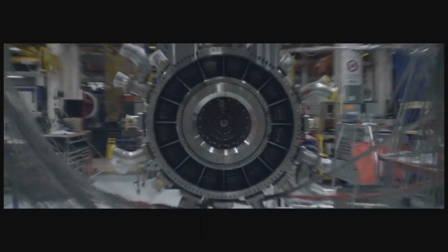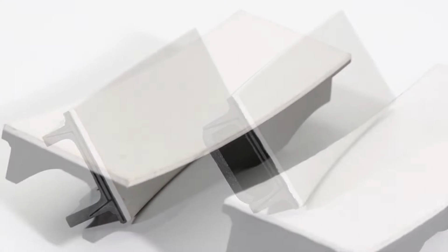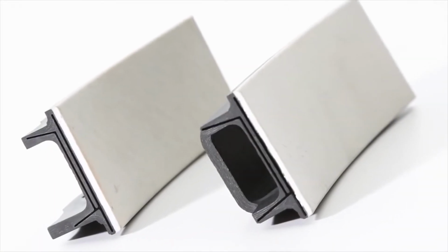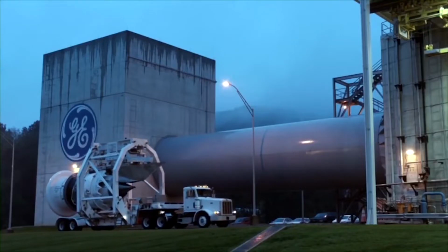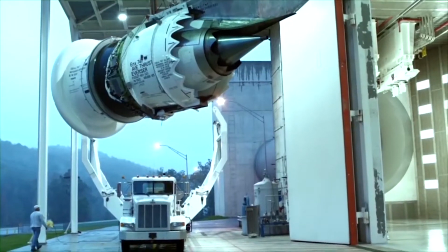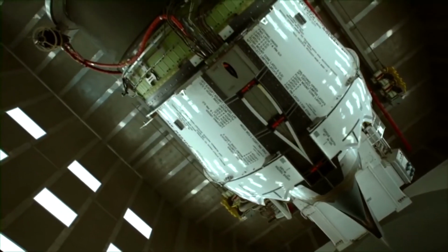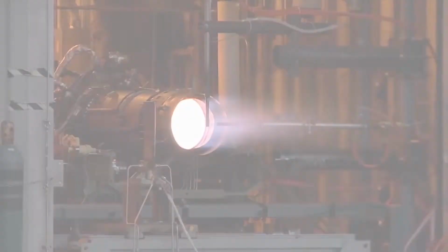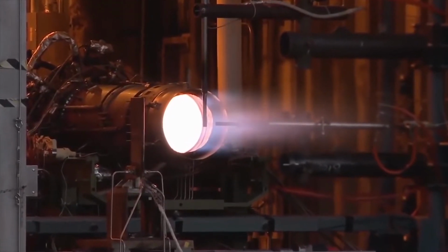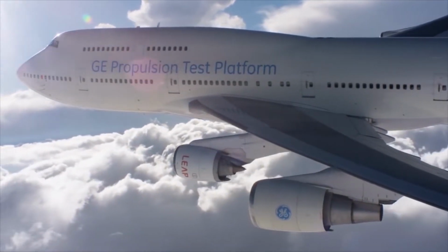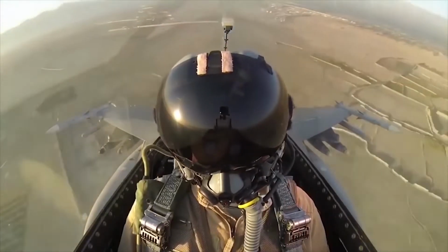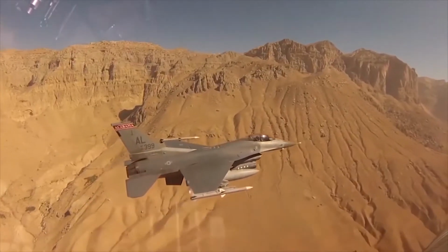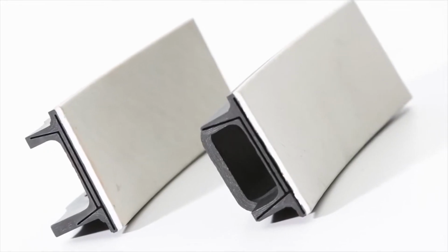For 20 years, GE has been at the forefront of CMC research, developing a material stronger than metal that can tolerate heat more than 500 degrees higher than any alloy, yet it weighs 2/3 less. CMCs are already at work in GE's newer jet engines and have so far racked up more than 1 million hours of flight time on commercial aircraft. Through a combination of hotter burn and lighter load, they're delivering astonishing efficiencies that translate into fuel savings, lower emissions, and better performance.